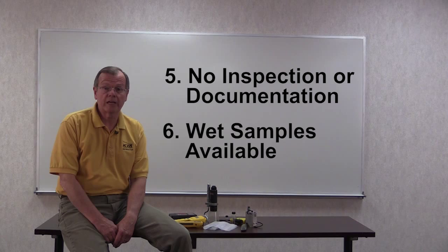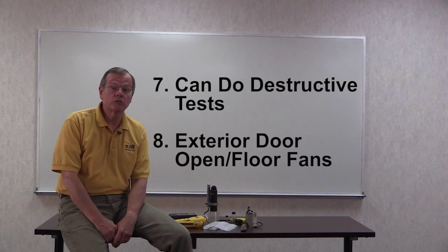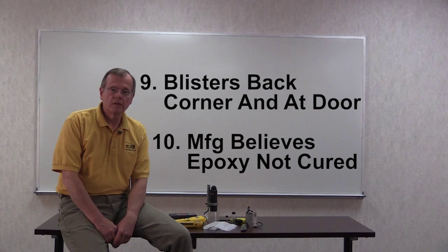No inspections were performed, nothing for moisture content of the floor, the ambient conditions during application, or the wet film thickness. Wet samples are available and you're permitted to do destructive tests. Ventilation was accomplished by one open door to the outside and fans blowing in during application and blowing out during final drying. The blisters were prominent along the back corner of the room and near the exterior door. The manufacturer believes the clear coat was applied before the epoxy had adequately cured.